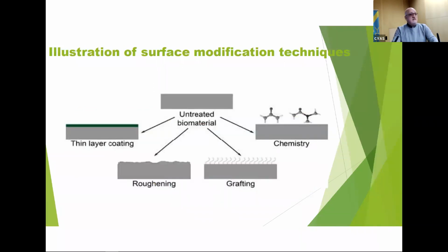To protect magnesium, we do have some kinds of surface modification. We have to modify the surface of magnesium. We have to know the chemistry of the coating we are planning to apply on this substrate to make some kinds of roughening of the surface. Roughening means I am preparing the surface of magnesium to be coated by the composite. That's roughening. And after that, to make a kind of deposition on this surface.